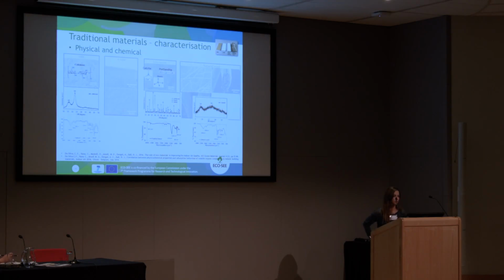I also assessed the chemical composition of these materials. We know that the radicals from the cellulose, like the OH, react with these VOCs, and also ionic species in the materials, like the calcium from the calcite. So not only the microstructure is playing a role in this adsorption-desorption experiment, but also the chemical composition of the materials.